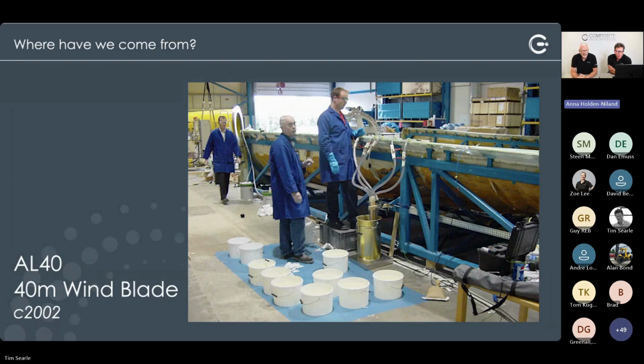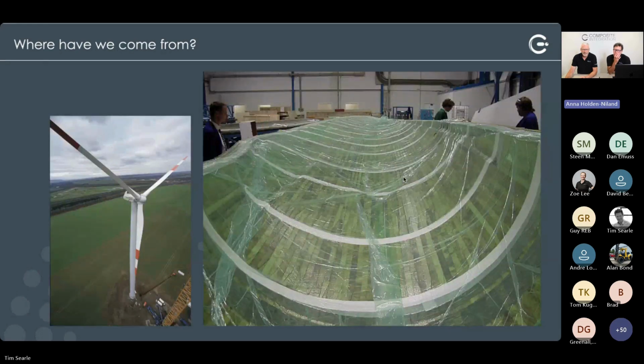In the photograph, you can see some 20 years ago, the development infusion of a 40-meter wind blade. This actually is an AL40, which was from Aero Laminates, which was then acquired by NEG Micon, which was then acquired by Vestas. Years ago, we did this. A lot of buckets, a lot of hand mixing, but actually things worked reasonably well. At the time, we measured flow rate, so we knew how much resin was going into the part. But on the whole, these infusions were very successful.